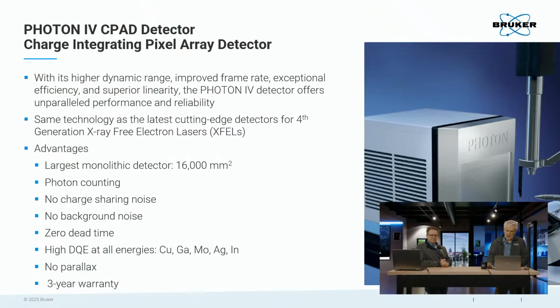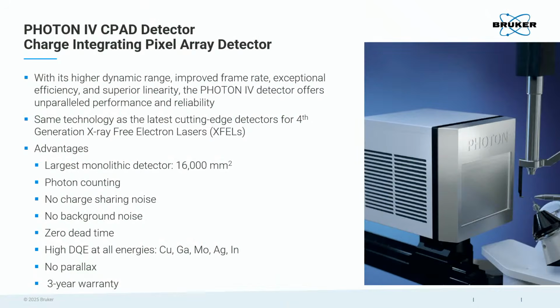The Photon 4, it's large. That's an important thing for detectors, right? Size does matter here. It really matters because you want to capture all the diffraction pattern. And the more reflections you have on a frame, the better processing works. It's very modern technology. We do photon counting in software that gives us interpixel logic. We can, for example, capture photons that are spread over multiple pixels when they hit at the interface.